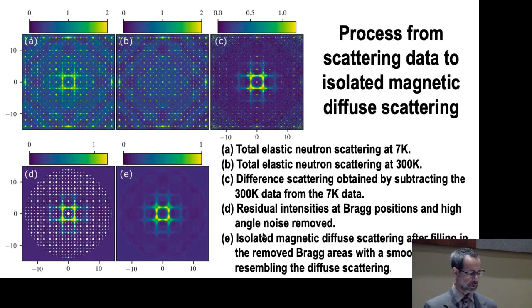But the process involves first extracting the magnetic diffuse scattering, which I showed you, but I'll give you a little more detail here. We again measure the total scattering, elastically discriminated, with the CORELLI instrument at both low and high temperatures, subtract the two, and you can see the registry of the Bragg peaks is not perfect. So we end up with some Bragg peaks left over. So what we do is punch and fill the Bragg peak positions with an interpolated density to smooth that out, and then we end up with something that we can work with to get the magnetic delta PDF.